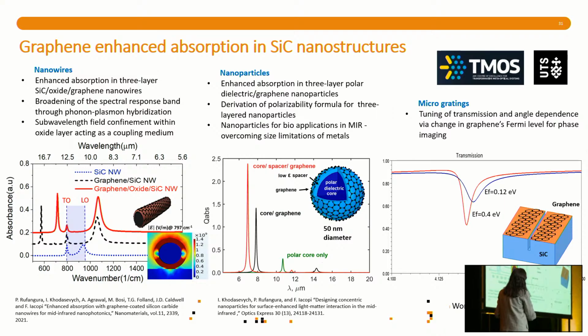We looked also at nanoparticles. We can play the same game with nanoparticles. We haven't made the nanoparticle, but we wanted to see whether that holds as well. And actually, we demonstrated there with a nanoparticle that if you have a silicon carbide core and graphene shell, you can increase the absorption in the IR. This is really interesting in case you want to apply this, for example, to nanomedicine, because if you want to work in the IR, the metal particles won't be that performing, whereas the silicon carbide system will be much more performing. The particles would otherwise have to be much bigger, and then you have a limit to what you can metabolize inside the body. So it also opens another interesting part of work.